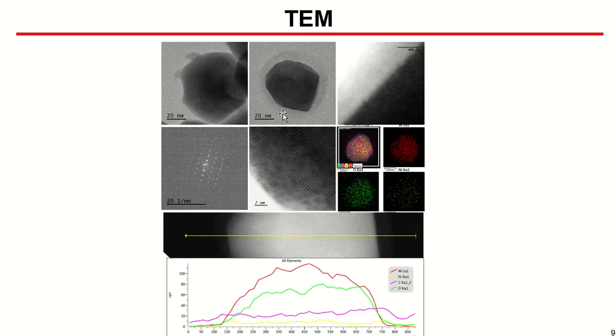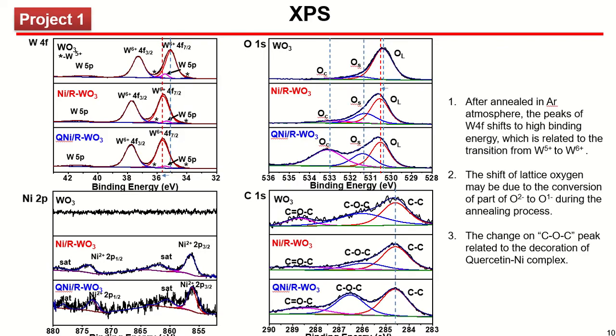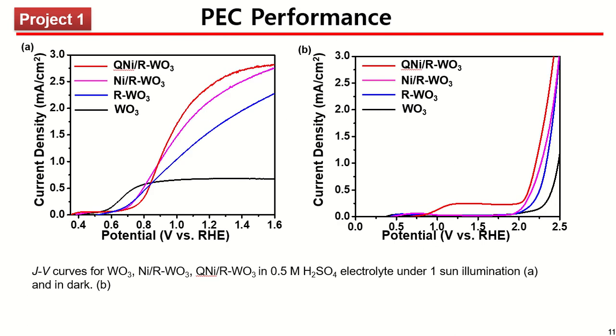Here we can see that a very thin layer is decorated on the surface of tungsten oxide nanoparticles, and our EDS mapping also shows that in the layer part, the carbon and nickel content is significantly higher than in other places. So, as we checked in our PEC performance data, compared to the bare tungsten oxide, our decorated samples show a very significant increase in water splitting performance at 1.23 volt versus RHE.